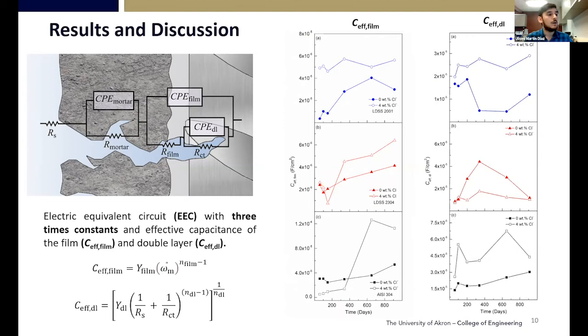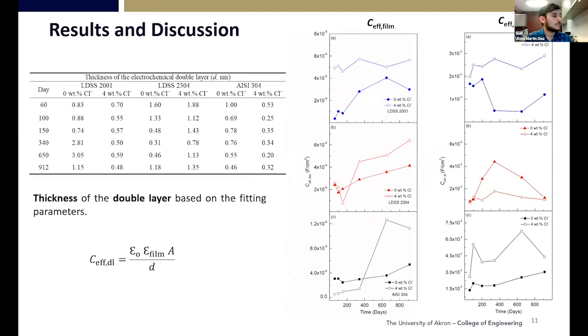As can be seen, most of the effective capacitance increases with the amount of chloride in the concrete, which could then be related to the passive film thickness by the equation here. Interestingly enough, the lean duplex stainless steel showed the thickest values of the double layer, even at the 4 weight % chloride, when it has the lower nickel content.